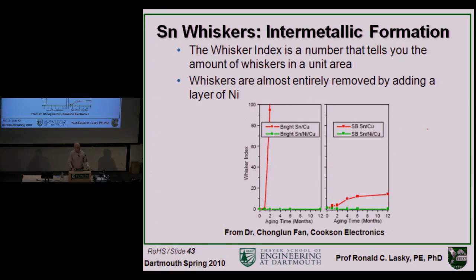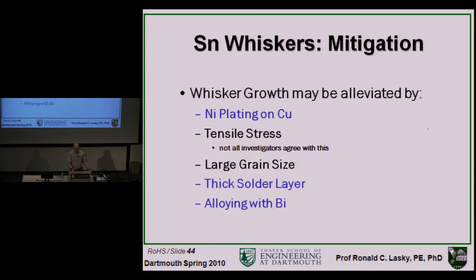So there are a lot of strategies for minimizing whisker formation, and I guess I'll review them before I give the summary on this. So if you put the nickel plating on the copper before you put the tin on, if there are ways to induce tensile stress into the compressive stress, that will usually alleviate it. A larger grain size will help. The blue is one that pretty much everybody agrees with. These are some that are still being debated. A thick solder layer. And anything that you can solid solution strengthen the tin with, like bismuth, like maybe 1% bismuth, will help quite a bit.